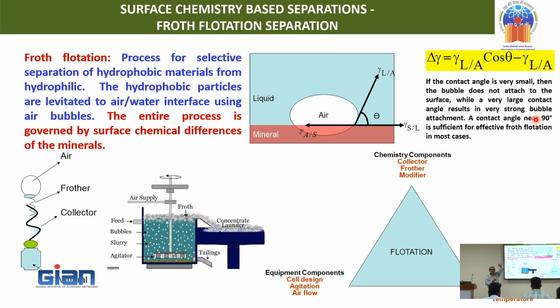Besides this levitation, the frother also helps in reduction of the surface tension on the surface, because the air bubble should remain stable on the surface for some time so that it can be scraped and taken into the concentrate launder. If it has to remain there for some time, the surface tension should be minimum. So the frother also helps in reduction of the surface tension on the froth structure, having a suitable froth structure so that whatever bubbles come to the surface remain there for some time, so that it can be scraped into the concentrate launder. Right? This is how it takes place.